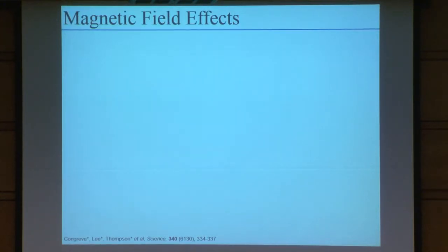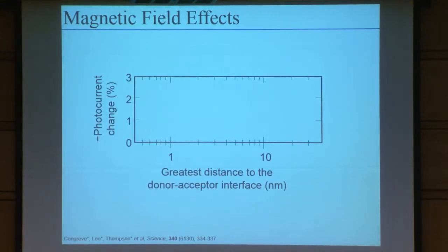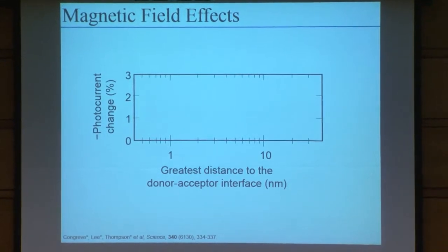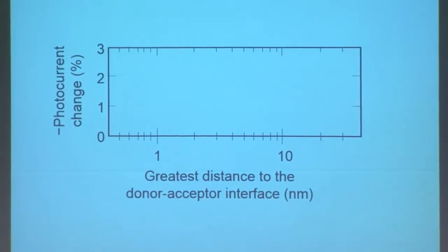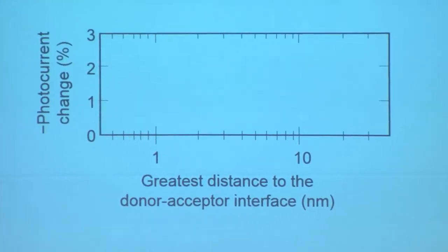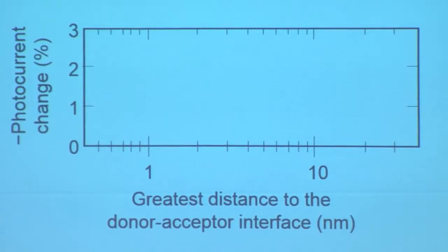And so we take that value at low field and saturation, and we can plot it as a function of different pentacene devices. So we fabricate a whole range of devices, from those over here that have very, very thin pentacene, such that every pentacene molecule is sitting next to a C60 molecule, and we go all the way up to here, where we have this huge, thick slab of pentacene that's very far away from any C60. And the idea here is that we can modulate these rates by doing that. In other words, when you're close to the C60, you expect exciton breakup to be extremely quick, whereas when you're far away, you expect the effective rate of singlet breakup to be extremely slow.